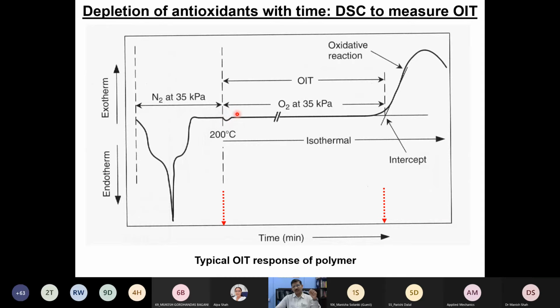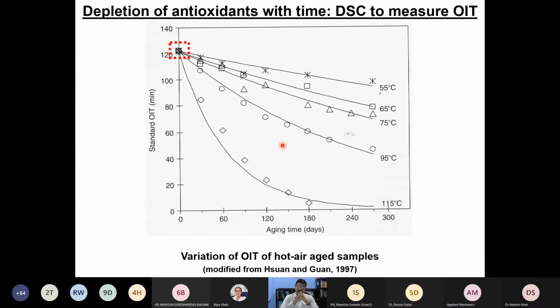Because of the oxidative nature of the oxygen, at one particular point we will see the oxidative curve. The time elapsed between the starting of the injection of the oxygen till this point is called the OIT value. Once you know the OIT, you can say whether the antioxidants are present significantly, then this OIT time is prolonged. If the oxidative time is really, really less, that means the antioxidant present in the system is very, very low. So by knowing this, what we did is we also measured